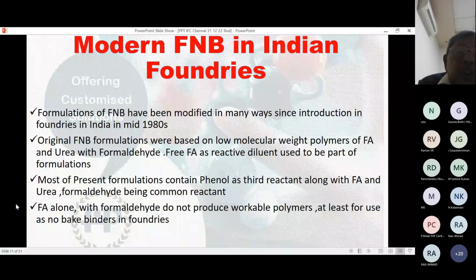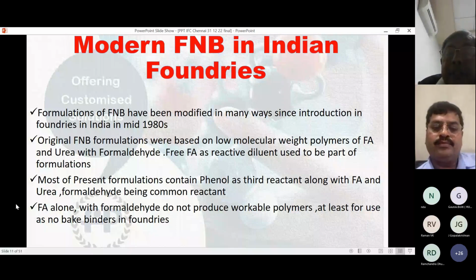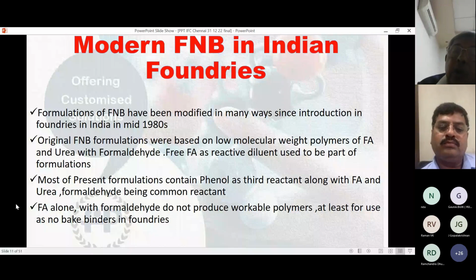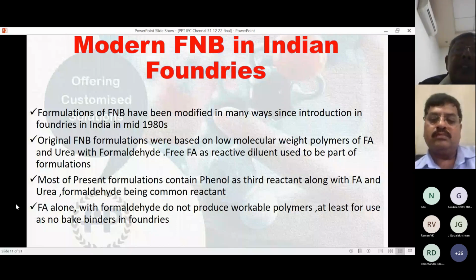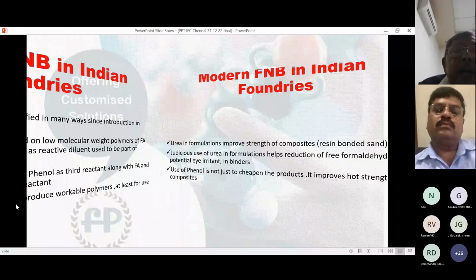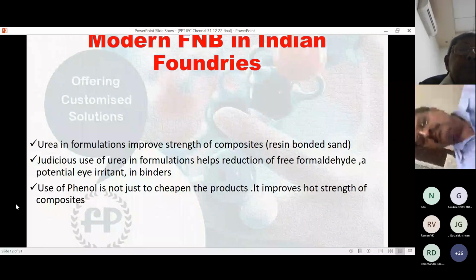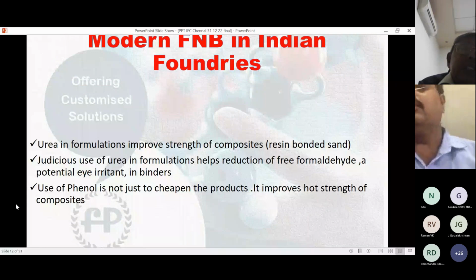Furfuryl alcohol alone with formaldehyde does not produce workable polymers, at least for use as no-bake binders in foundries. That means furfuryl alcohol, although it's possible to react with formaldehyde in different pH conditions, does not form a workable polymer as no-bake binder in foundries. You need to add either urea or phenol or both. Urea in formulations improves strength of composites. Composites mean resin bonded sand, that is molds or cores.